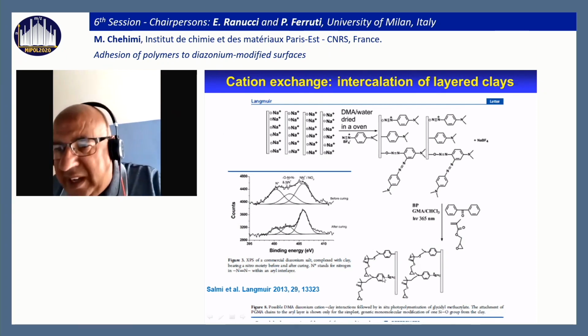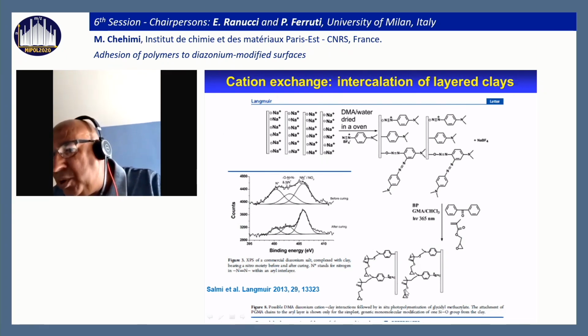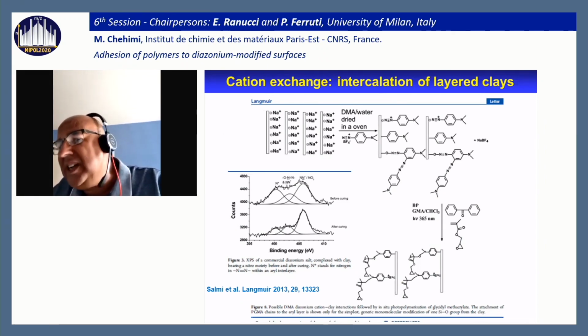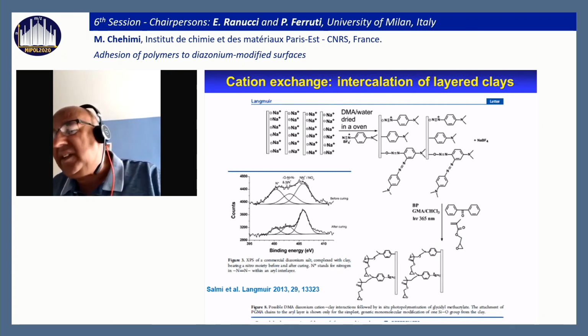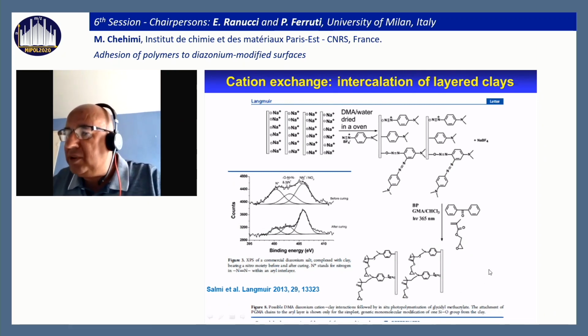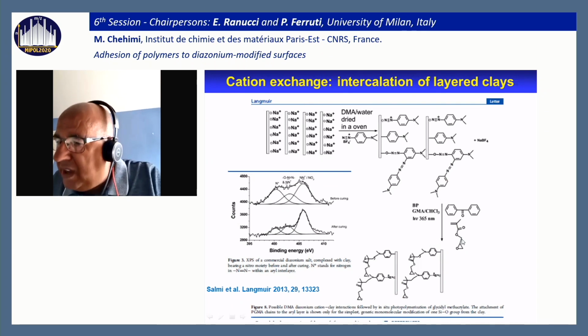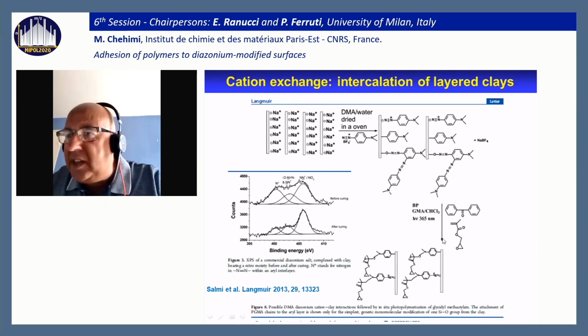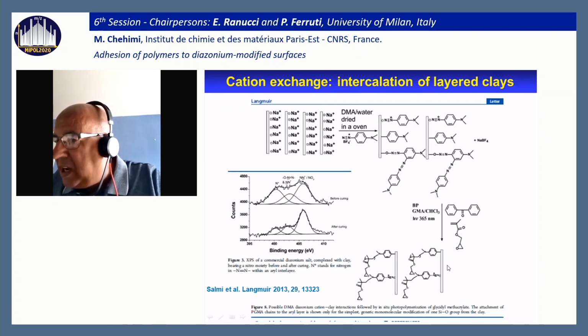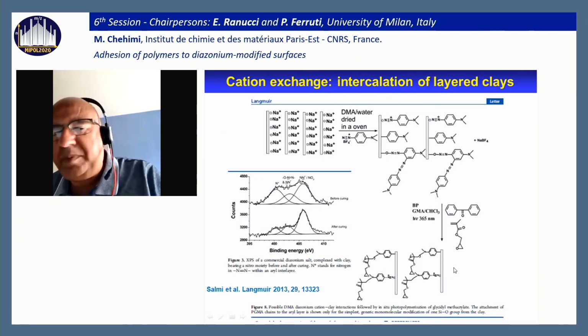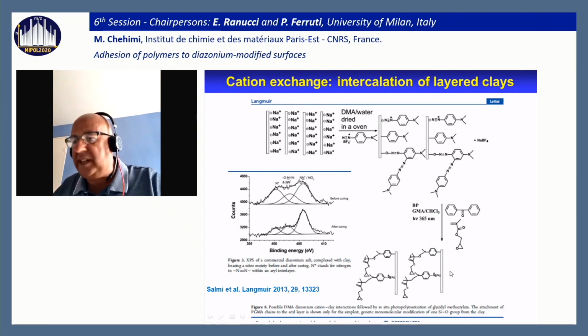And from that, we have done some photopolymerization to make clay-polyglycidyl methacrylate nanocomposites, which could be used as a filler, actually a reactive filler, because here you have a lot of epoxy groups borne by the lamella of the clay, and this could be used, as I said, as a reactive nanocomposite filler.